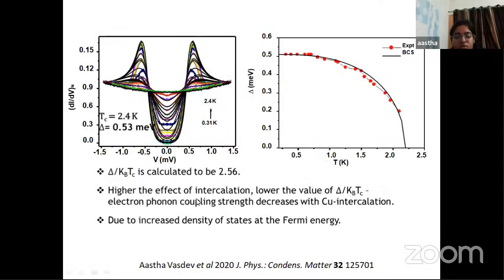While in our case, we can rule out the possibility of enhanced electron-phonon coupling strength by looking at the value of Δ/kBTc, which decreases with copper intercalation. Hence, we can say that in our case, the enhanced Tc is observed because of the increased density of states at the Fermi energy.